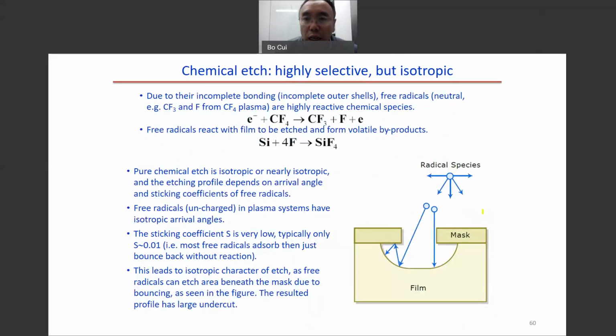So now let's look at free radical chemical etching and ion physical etching separately. For the chemical etching, normally it is very selective but isotropic. Very selective means the etching rate of different materials is very different. For example, if we use oxygen gas, it can etch away the polymer very fast, but it will not etch silicon or metals. That means the etching rate is very different between the metal or silicon and the polymer. So this is called high selectivity.